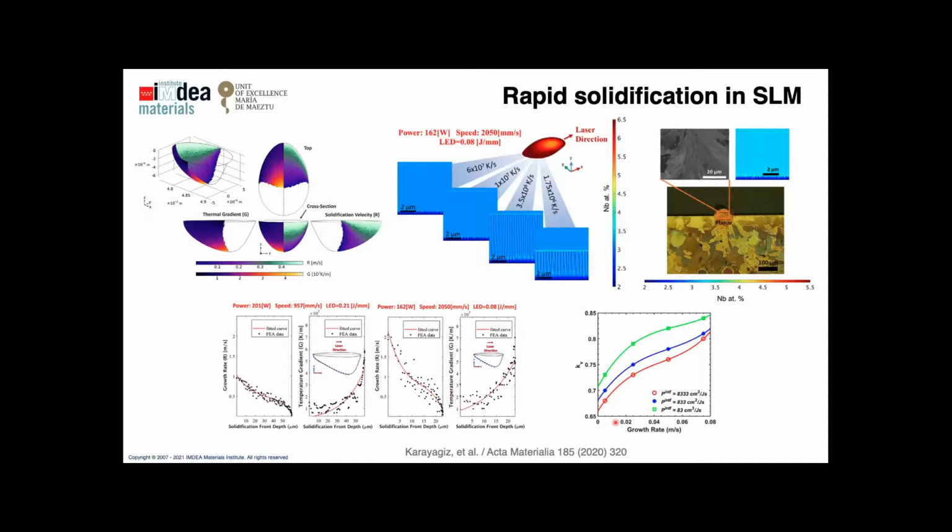And another takeaway from that paper is that the authors conclude, okay, but we don't know what to take for this permeability coefficient. Look, we change it by orders of magnitude because we don't really have a guideline about how to choose it, and we get notably different partition coefficient versus growth rate. So, okay, that's pretty much what's out there.